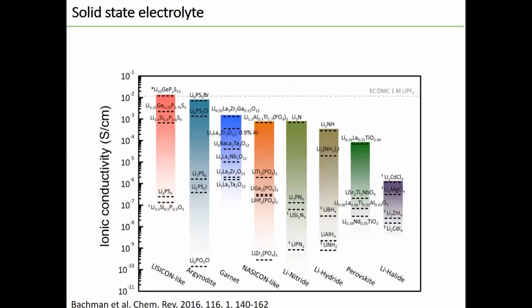Solid-state electrolytes have been widely studied for a long time. Based on their composition, they can be classified into ceramic, polymer, and their composites. In the past, solid-state electrolytes were limited by their low ionic conductivities, which is lower than 0.1 millisiemens per centimeter, while organic liquid electrolyte exhibits a much higher ionic conductivity of 10 millisiemens per centimeter.